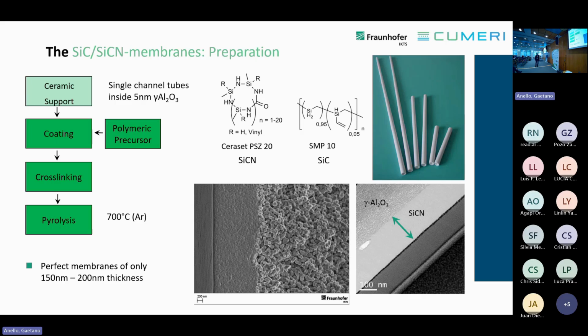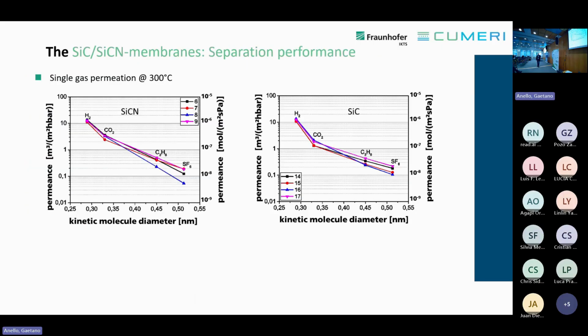And we got very nice layers. They look very perfect, thickness 150 to 200 nanometers, very, very thin and very, very smooth. The smoothness is, of course, related to the gamma alumina layer that is below. Then we made single gas permeation tests at 300 degrees C. As you can see, in both cases we got very high hydrogen permeances in the range of 10 cubic meters per square meter hour and bar, which is equal to 10 to the minus 6 moles per square meter second Pascal.